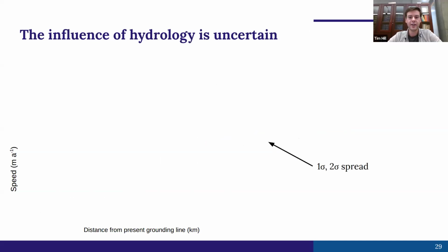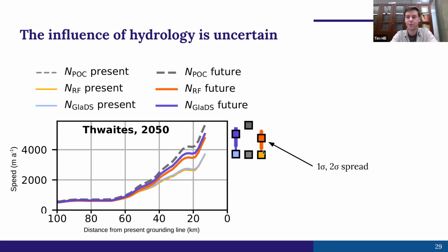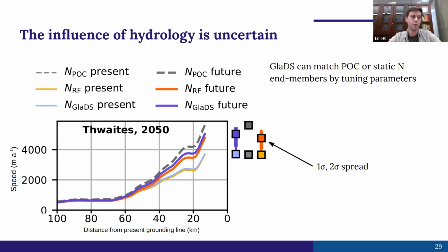We can also add on here the uncertainties associated with my perturbed parameter ensemble. Here, these vertical bars represent the 1 and 2 sigma spread when I sample from a wide range of GLADS parameter values. And the square markers are just copies of the grounding line speed for all the curves for reference, because it's easier to look at that way. What I find is that by tuning parameter values, you can either make GLADS as sensitive to changes in ice thickness as the perfect ocean connection model, which in most cases overestimates the speed up, or you can make it as weakly sensitive as effective pressure just not changing in time. So while we have one estimate here in the figure of what I think the impact of hydrology is, it's actually still quite uncertain.